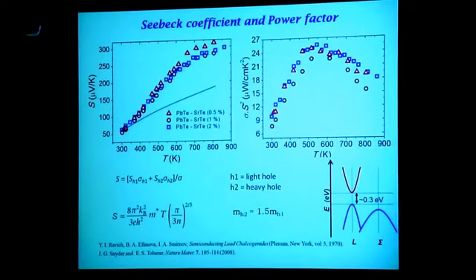So this is the thermal power of the system. It's positive, so it's p-type, that's what you expect. And what is characteristic about this is the very sharp rise of the thermal power from low values at room temperature to very high values at 800 degrees. And this very sharp rise is where the two bands come in. Both are contributing and you get the sharp rise. If you only had one band, the rise would have taken this path here. So the second band is contributing as well to get the very high thermal power. Along with the high mobilities that give us high conductivity, we got a very high power factor for these samples. And whether they have 0.5%, 1%, or 2%, we have a similarly high power factor.